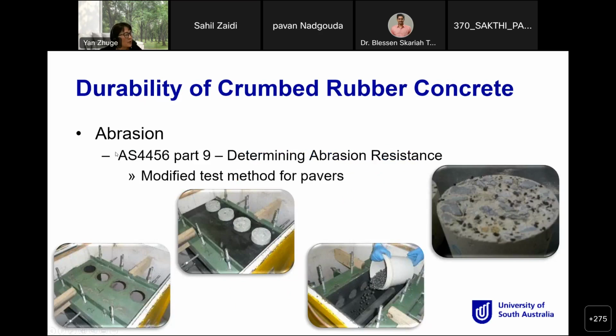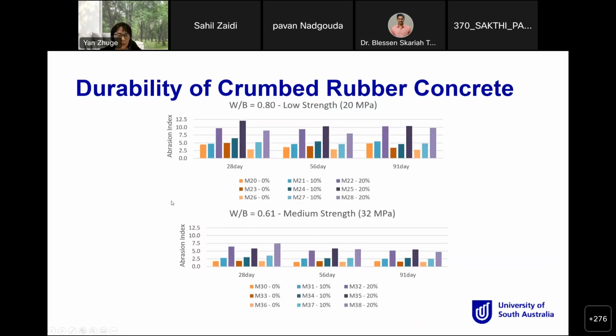So the last one we did was the abrasion test to determine the abrasion resistance. We're using a modified testing method based on a paper, because there is no such testing method available for normal concrete. And from this test, we found that all the low strength crumb rubber concrete mixes show an increase in abrasion index regardless of the binder type or the age tested. So this suggests that crumb rubber has a negative impact on the abrasion resistance. For the 20 megapascal lower strength one, you can see at 10% the average index is still okay, but when you go up to 20%, there is a significant increase. So that is probably the only negative effect on the durability performance of concrete.